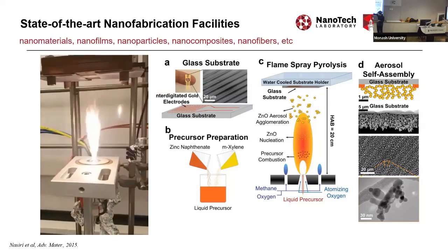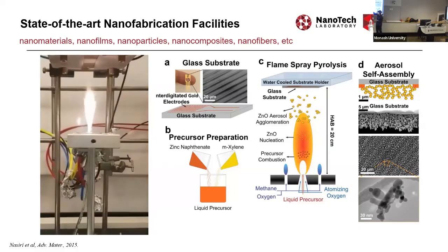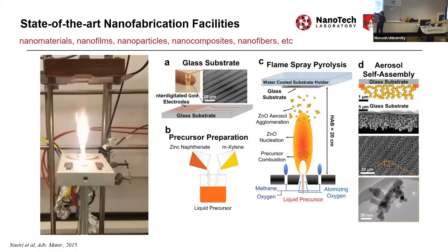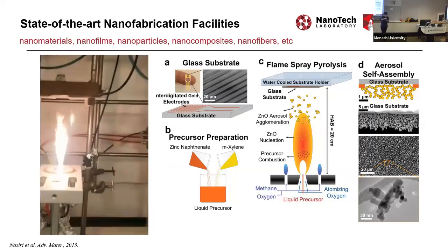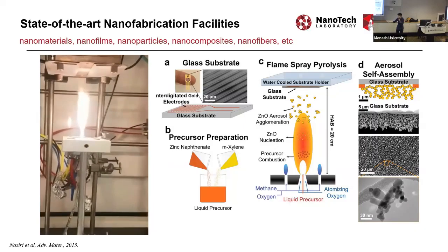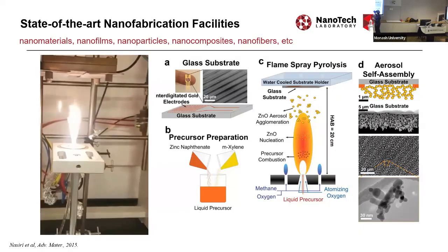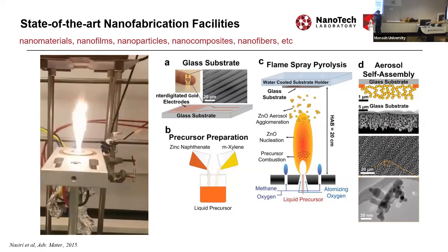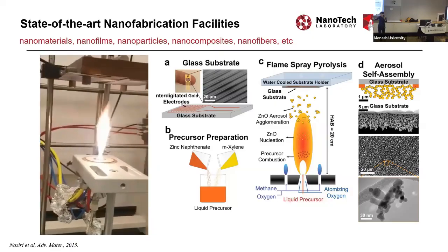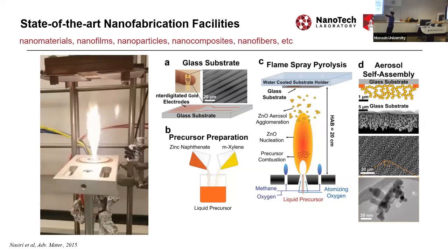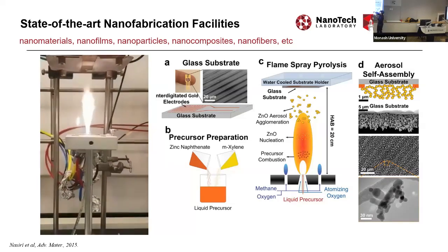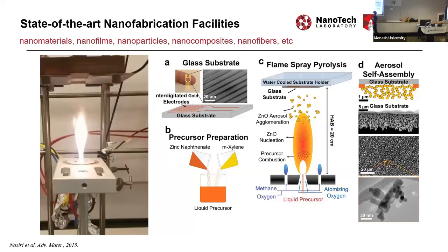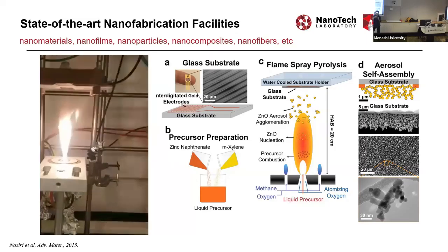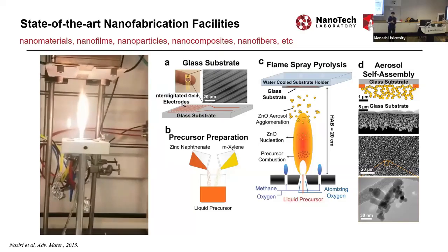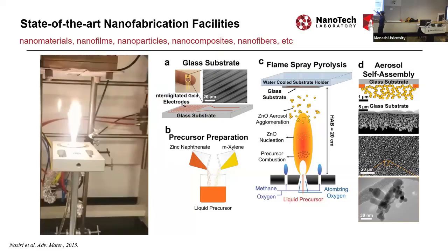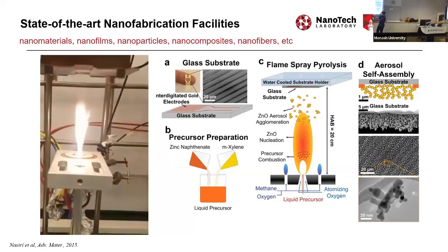Then I purge them through the system over there. Then there is a pilot fire, but the middle fire you see in the middle, which is a very obvious one, is the precursor being injected into the system, atomized using this oxygen. When the droplet is coming out of the needle, the oxygen with a high pressure hits the droplet and atomizes it into extremely tiny droplets. Then the combustion happens inside the fire, then the nucleation happens, and by the time this precursor is coming out of the fire, you have a lot of metal oxide created over there.